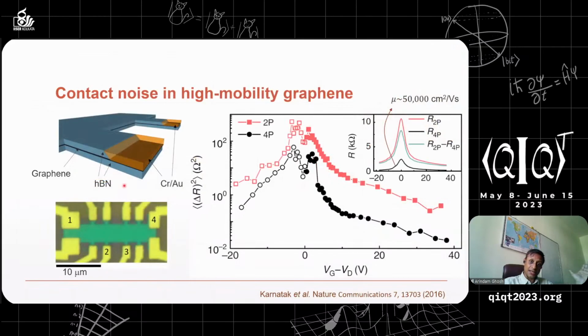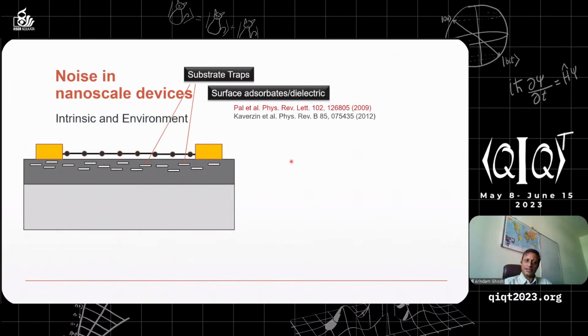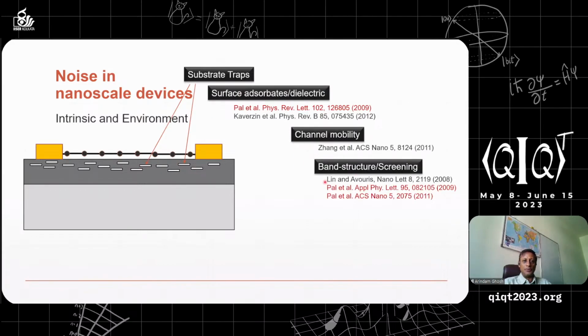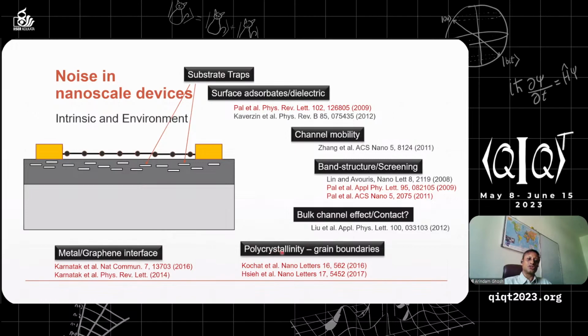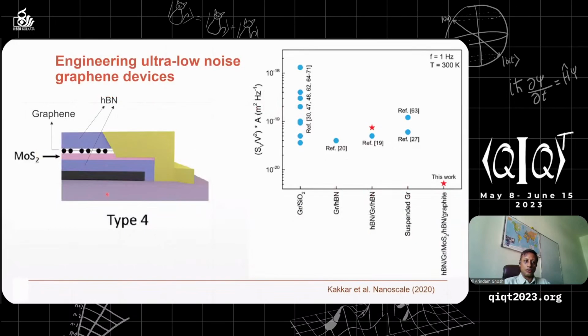In addition to that, we find the contacts are extremely important, that you need to have non-invasive metal contacts in order to reduce the dephasing and the noise in two-dimensional materials. Overall, our understanding over the last several years on this topic shows that there are lots of new noise sources, which is why we need to improve the devices. We need to improve the traps in the substrate. We need to improve the channel mobility. We need to use proper contacting strategies. We need to make the graphene single crystalline, and of course, the interface of the metal and graphene requires care. All this work we have done over the last 2 years has allowed us to come to an optimal strategy of creating ultra-low noise graphene devices, which now have a record low noise in the literature based on two-dimensional materials.